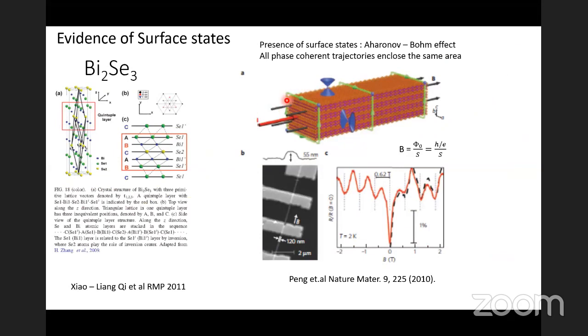The presence of a surface state has been shown through a number of very interesting experiments. One of them is that you can take a nano ribbon of Bi2Se3 and apply a magnetic field along the nano ribbon. This red line shows the magnetic field along the nano ribbon, and you will see oscillations in the magnetoresistance. These oscillations correspond to the Aharonov-Bohm effect, where there are phase coherent trajectories enclosed around the surface. For example, these green trajectories are the surface currents flowing on the surface, and all of these surface currents enclose the same area, because the oscillations in magnetoconductance happen at integer multiples of the magnetic field, phi naught, the flux quantum, divided by the area of the surface enclosed by these trajectories. So it is h cross by e by S, where S is the surface area. This shows that there are conducting surface states on Bi2Se3.